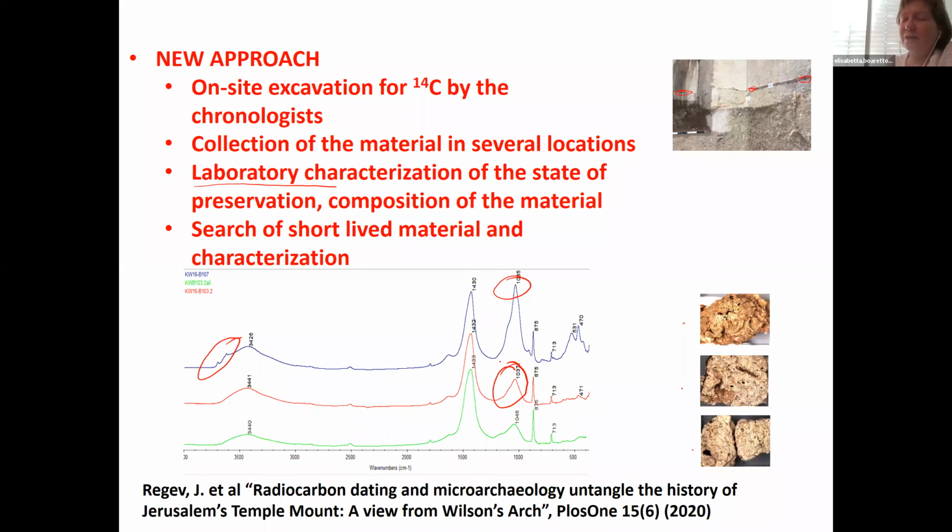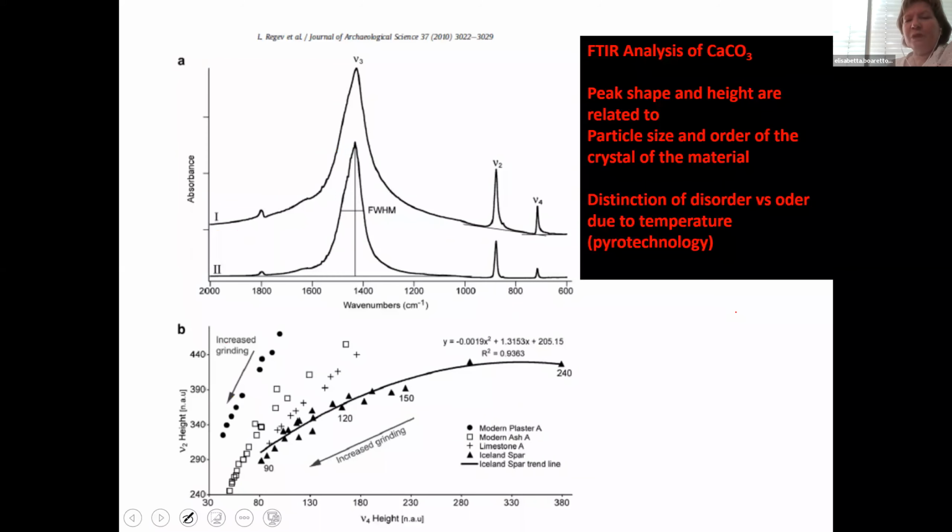Maybe broken ceramic was added, but the peak of the clay is 1037, and we don't have the structural water. So these are all methodologies that we have built through time to understand better the archaeological material. And we check if this is reproduced for all the mortars in the same layer, in the same structure.